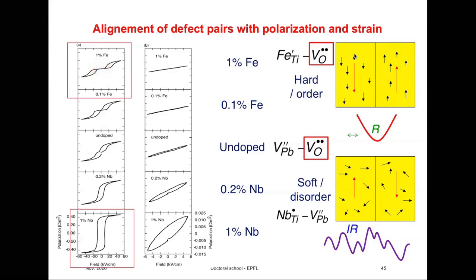It's an experimental fact. For a soft material, donor-doped, niobium-doped material, we draw the conclusion from this experiment here that defect dipoles must be randomly distributed in space with different strengths. And therefore, the domain wall moves in a potential like this, while in a hard material, the domain wall is really sitting in a very deep potential. This is valid for weak fields. Of course, this breaks at large fields. Okay, so that's the picture that we can propose, and now we have to prove it and find additional experimental evidence that this qualitative model actually works, and that we will do next.